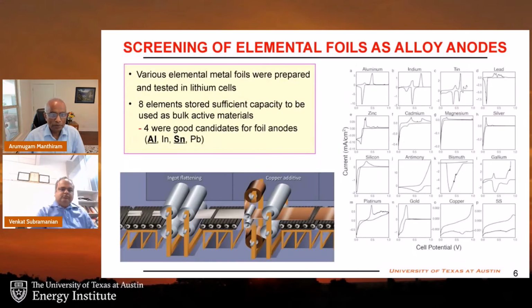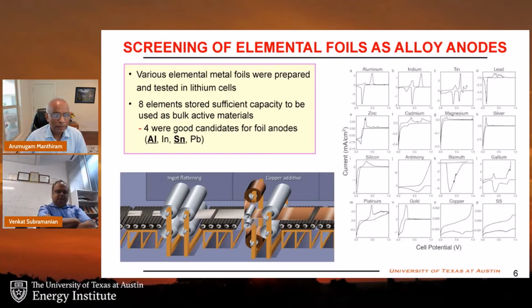So with this approach, we have tested actually several materials, metals, as you see here, aluminum, indium, tin, lead, and other things. In that, we found 8 elements have sufficient capacity to be used in this process. And in that, we select just 4, particularly aluminum and tin, and indium and lead can also work, but lead is toxic, and indium and tin are heavier than aluminum, for example.